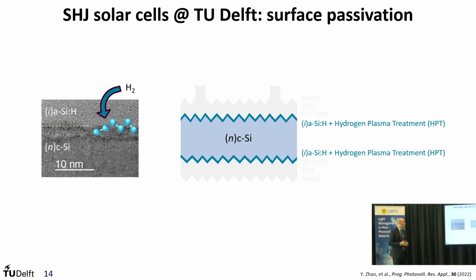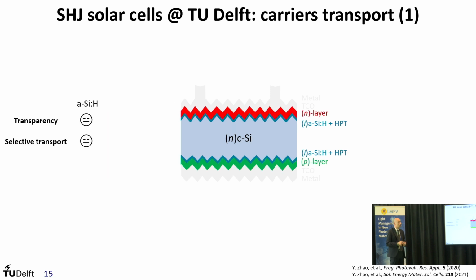So here we had to tune a number of parameters, and then we also learned how to back etch and then re-deposit amorphous silicon in a way that our key performance indicator, that is the lifetime of minority charge carriers, could be maximized. So by only using these two very thin layers of about 4 to 6 nanometers, we could get routinely 10 to 11 milliseconds.